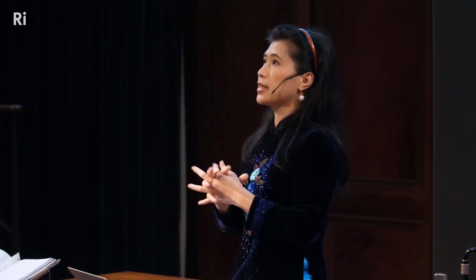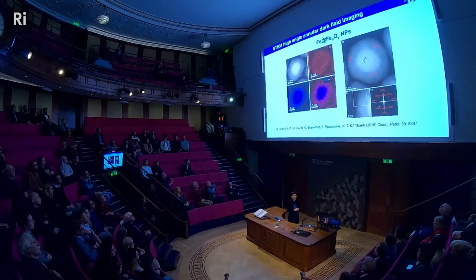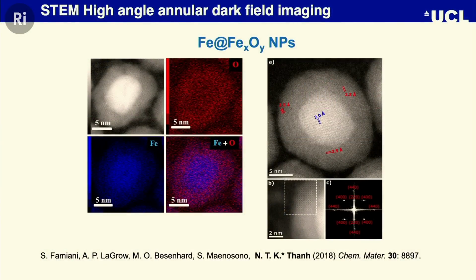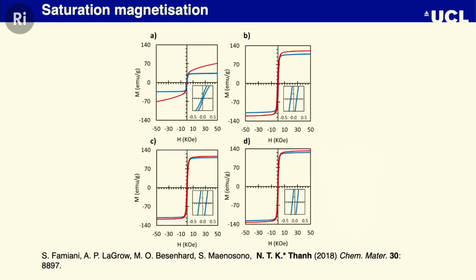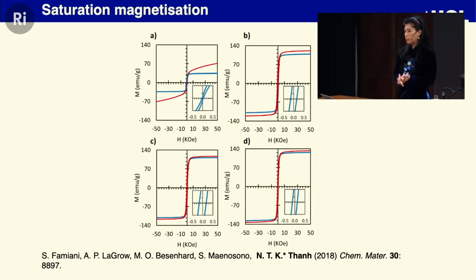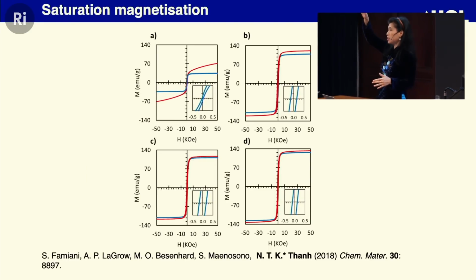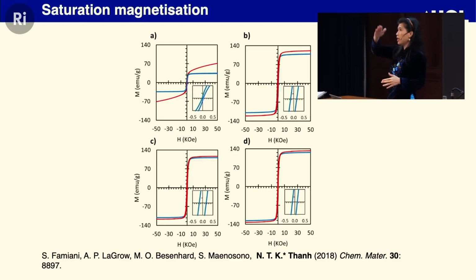But then you look in the scanning transmission electron microscope for elemental mapping, you can see that the red signifies oxygen, and the blue signifies iron, and you overlay them, and you can see clearly that inside you have more iron. So you have this core-shell structure. We also characterize them for the saturation magnetization that I mentioned before. You can see the curve there, it's going up and it's saturated. And so we characterize the magnetic property as well.